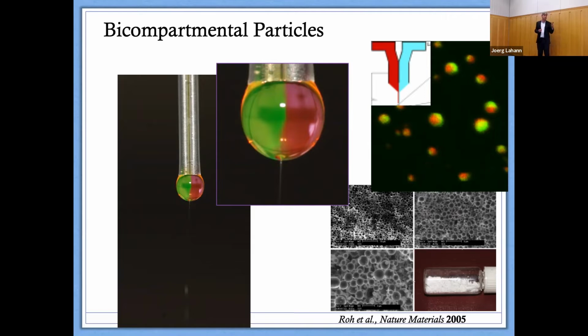It's fine that this is completely dilute, because through my precipitation, I end up with a solid matrix that basically sequesters my drug, right? So in the context of what I'm going to be talking about, this could be a polymer with a siRNA, for instance. And this could be a small molecule drug like paclitaxel. And you can combine them and create particles that basically deliver both, but with different kinetics, because the kinetics I can control by the choice of the matrix and the drug.